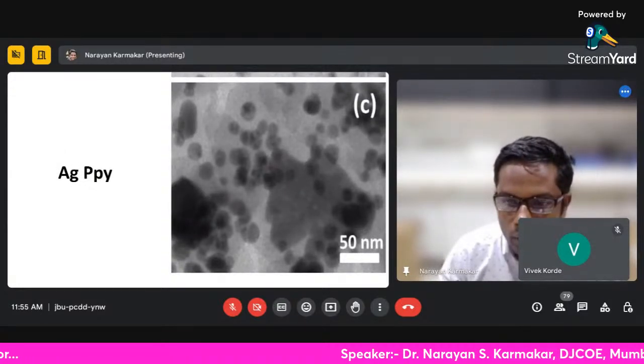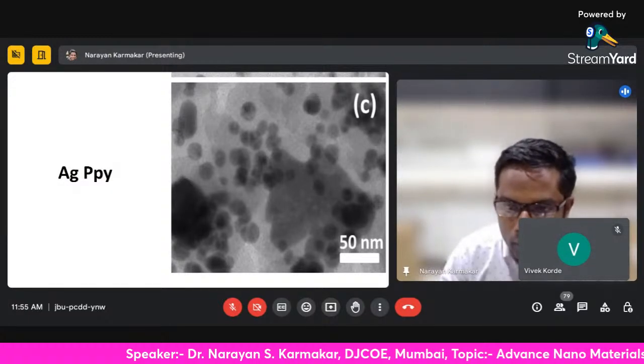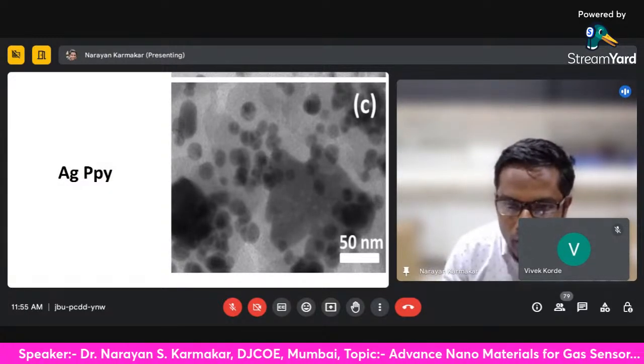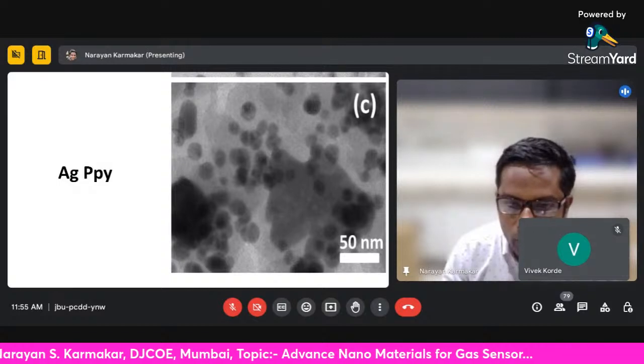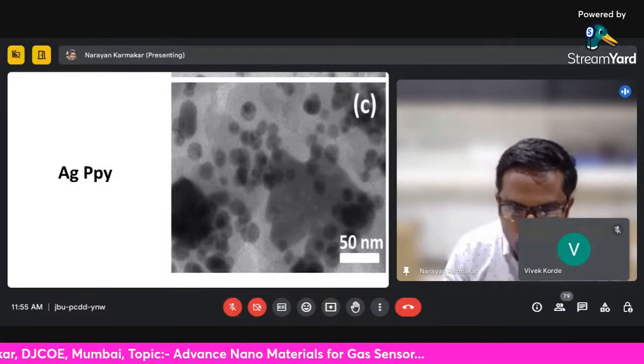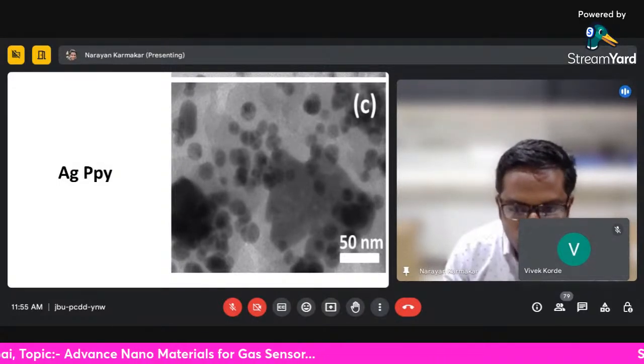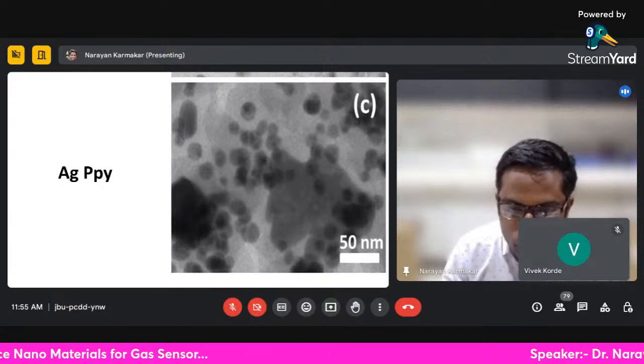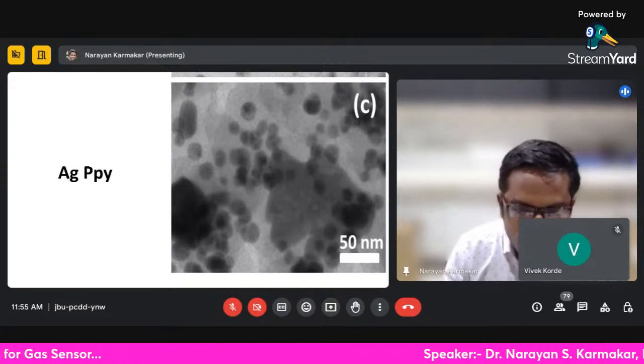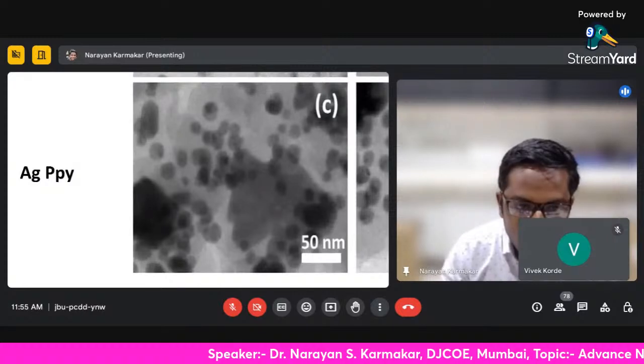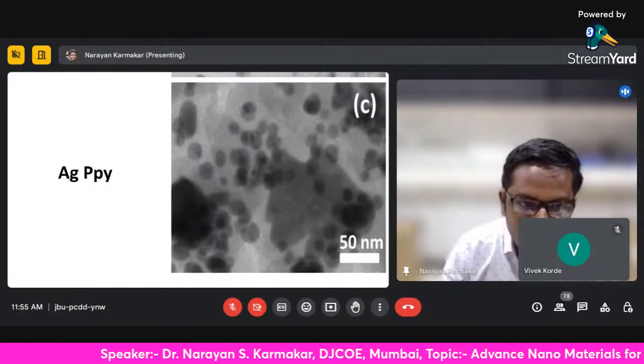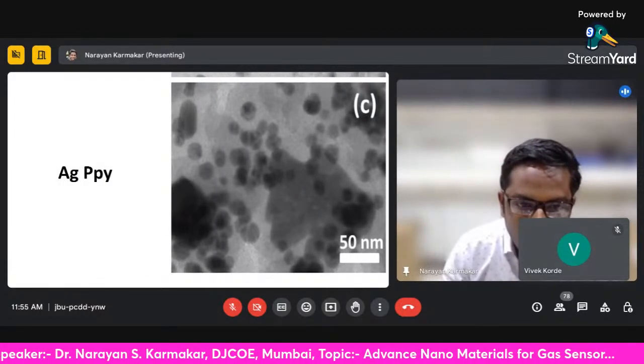We can see that the polypyrrole-coated silver nanoparticles, the difference in contrast, clearly indicates that the silver nanoparticles are well dispersed in the polymer matrix with minimum agglomeration, which plays a crucial role for efficient charge transfer in the conduction process within the polymer matrix. Because of this, the nanoparticles are well dispersed.